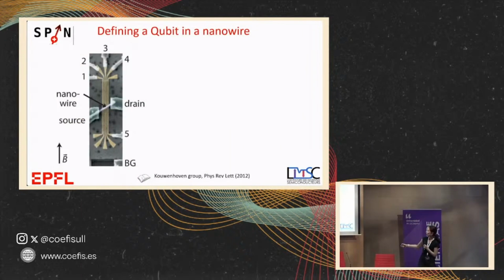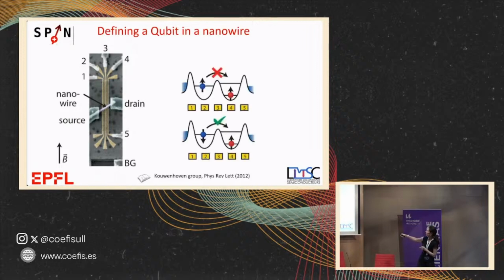So you have one of these nanowires, and this is a different material, but it's one that you can take freestanding and put on a substrate. And this is all very small, so it's complicated. You put some electrodes below, and with the electrodes, you elevate the potential in different regions. When you do this, if you look at the potential for the electrons, you see it's like mountains. And they like to be in the lower states. As it's very small, there are quantized states, so they cannot occupy all the states, so you have them here.